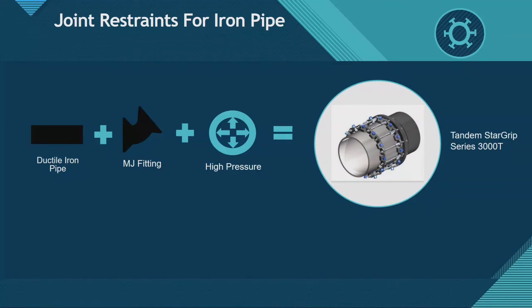If you need to get higher pressure ratings, you can use what's called a tandem restraint. So it's two wedge action restraints back to back into an MJ fitting. This is most common on 18 to 24 inch, where the fitting is rated to 350 PSI and the restraint's only rated to 250 PSI. In order to get that rating up to 350 PSI, you need to do it in tandem.